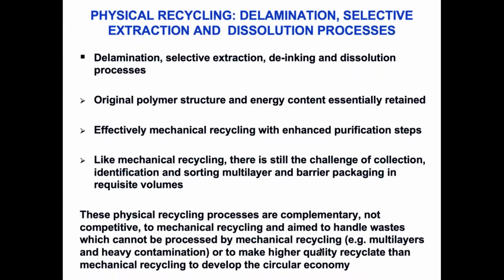Moving on from mechanical recycling now, what I call physical recycling, although some people will call this chemical recycling. These are things like delamination, selective extraction and dissolution processes, which can also provide de-inking. Here, the original polymer structure and its energy content are retained, essentially just like mechanical recycling with enhanced purification steps. So we still have the challenge of collection and identification and sorting to get enough volumes to make it economic. And these processes are complementary, not competitive with mechanical recycling, and they're aimed at handling waste that cannot be processed by mechanical recycling, such as multi-layers and heavy contamination, and to increase the quality of the recyclates.